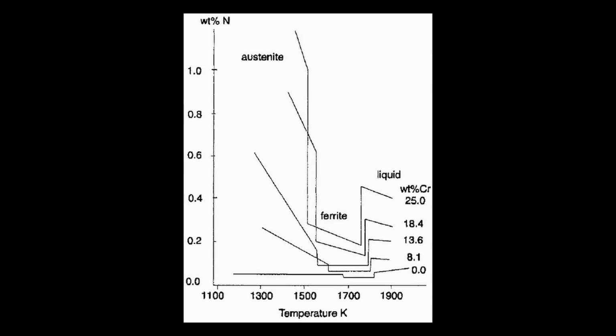And it's relatively easy for them to add it, at least in these kinds of amounts. As for nitrogen, it's hard to get it into liquid steel. It's not very soluble in liquid steel. So you add in gaseous nitrogen and it just floats on out of the steel. But in a small amount like this, they can pump in a little bit of nitrogen and it'll stay in there. Is there a simple explanation as to why you could share with people? Somebody smarter than me would have to explain that. But different elements have different solubilities in different solutions.